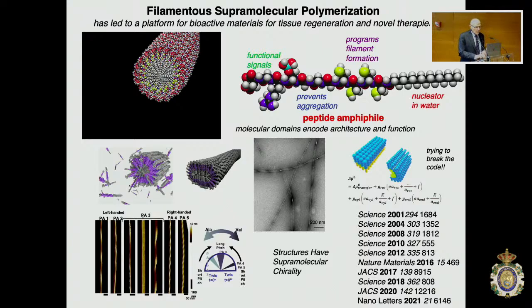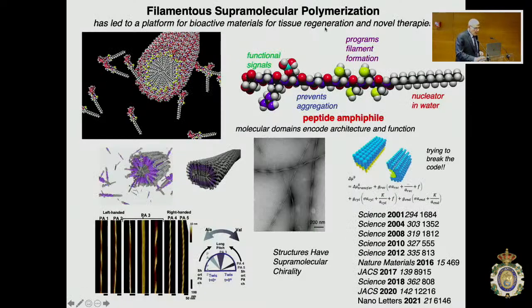So the molecule, you see it at the top, this is the monomer, and the monomer has a peptide sequence, and when the self-assembly occurs, if you put a signal at the very end of the molecule, then you can display that signal in an incredible density, upwards of 10 to the 15th power per square centimeter. So it's a very interesting strategy that can create highly bioactive materials if you put a biological signal, but you could put a chemical signal or anything else that you want.